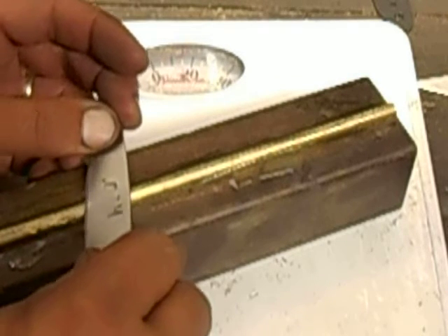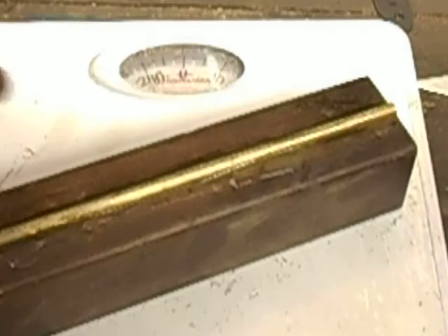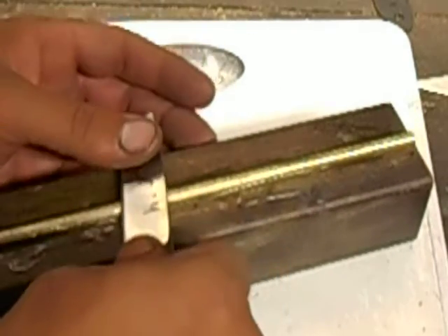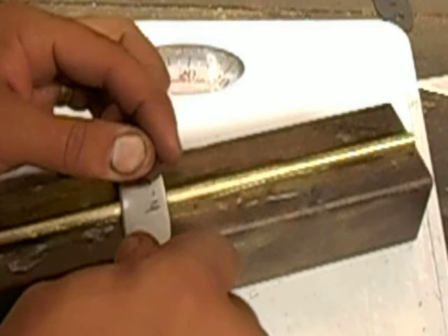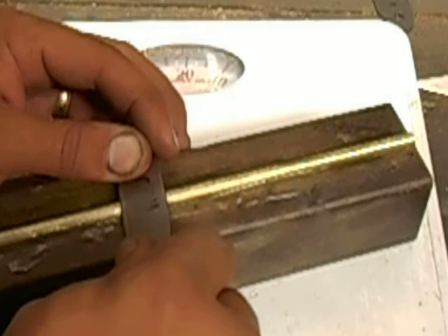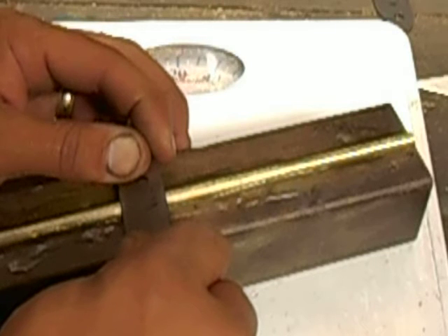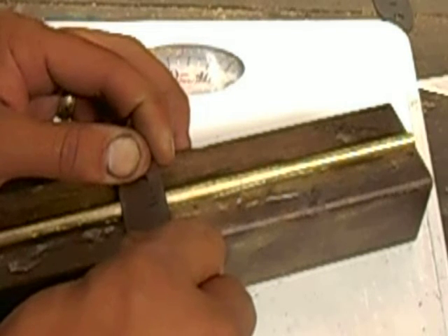So now is where we break out the safety glasses, because if it chips, that chip will go flying off. Yeah, we're still at 15 to 20 pounds to complete an edge flex. It will pass it on both sides. And I'm not hearing any chipping. I'm not seeing any chipping. It's doing really good. So now let's go ahead and force that edge to get damaged and see what it takes. So about at that angle, nothing. And then we'll keep increasing the angle. There, it's flexing pretty good. It's flexing really hard. We're at about 30 pounds.